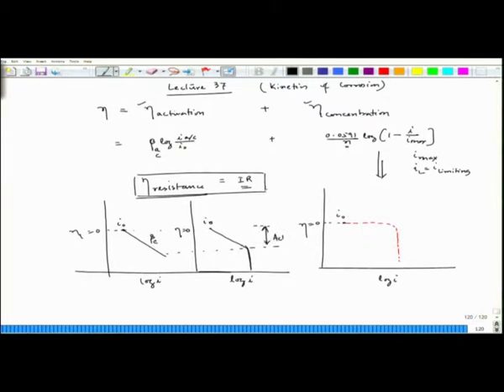So this part is activation and this part is concentration polarization. And we have also seen that this concentration polarization actually depends on several factors: of course the type of metal, metal surface, agitation, temperature, all those will have effect on this I max. This particular current is I max, since once I max is reached, you see that this over voltage becomes infinitely large. So when it reaches I max, it actually drops vertically with reference to the log I axis. That means this point is also I max.